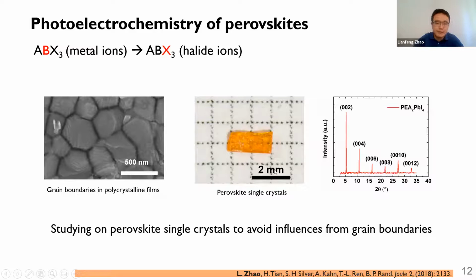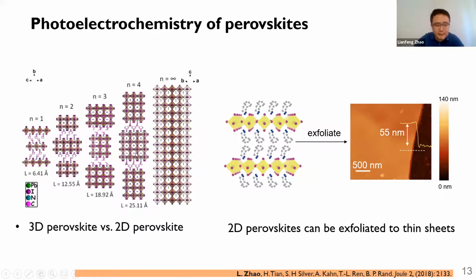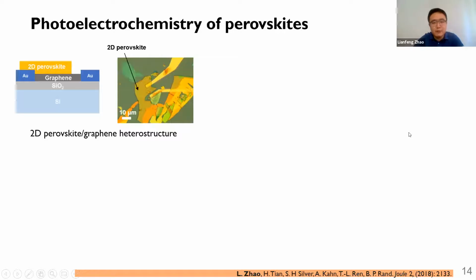What we do is use a so-called 2D perovskite, which basically uses organic cations to slice down the 3D perovskite crystal structure and make a layered crystal structure. And the van der Waals forces between these organic molecules allow us to exfoliate it into thin films. So basically we make very thin crystals to be more sensitive to the surface chemistry. And furthermore, we fabricated electronic devices to probe the chemistry on the surface very sensitively.